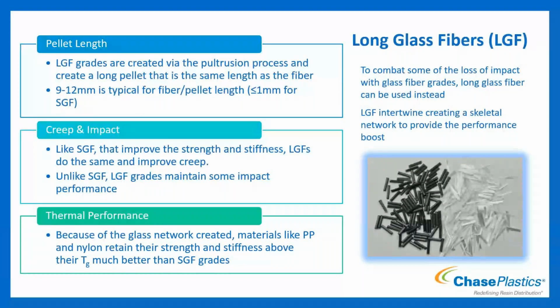So all this to say: long pellet allows for an increase in stiffness and strength that you'd get with short glass, but you also get a little bit better creep performance, you maintain some of your impact, and you see better retention of mechanicals past the TG of the base resin.